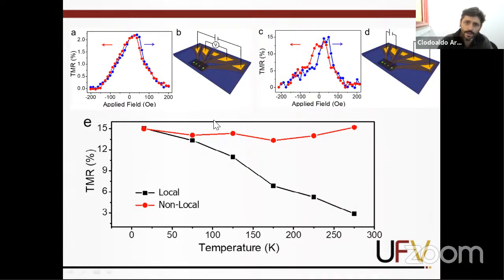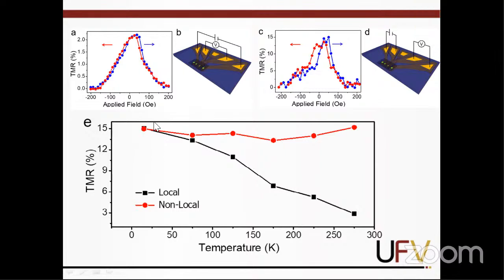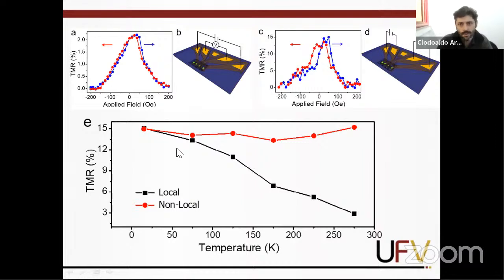So here we compare the pure spin current and the spin polarized current made by local configuration and non-local configuration. And then we see that the pure spin current has not much influence from the temperature, but the spin polarized current has. At low temperature, both are the same.